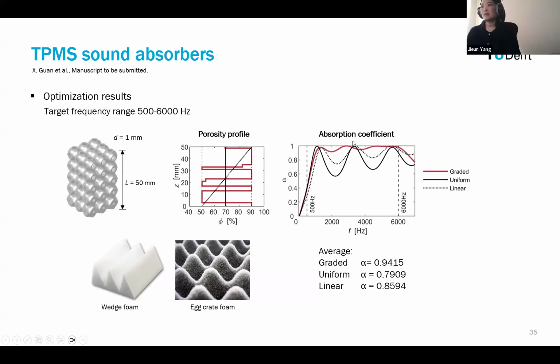So you can see that the linear grading can actually improve the sound absorption in between this absorption peak, but not so significantly. But by using this optimal grading, we can actually improve the sound absorption coefficient quite significantly. And these are the values of the average sound absorption coefficient within the target frequency range.